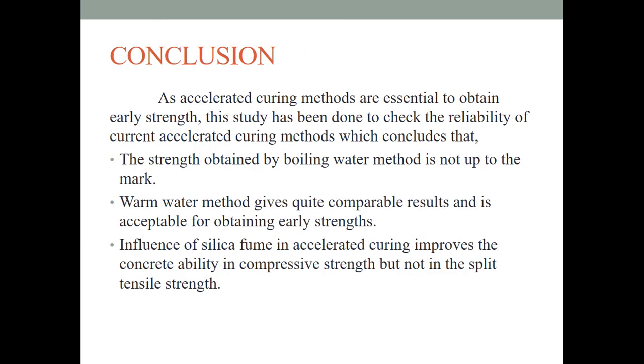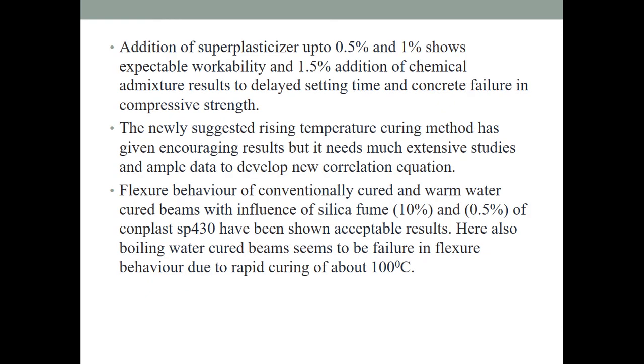The strength obtained by the boiling water method is not up to the mark. The warm water method gives quite comparable results and is acceptable for obtaining early strength. Silica fume in accelerated curing improves the concrete's compressive strength but not the split tensile strength. Addition of superplasticizer up to 0.5 and 1% shows acceptable results, while delayed setting time and a failure in compressive strength are seen at 1.5%.